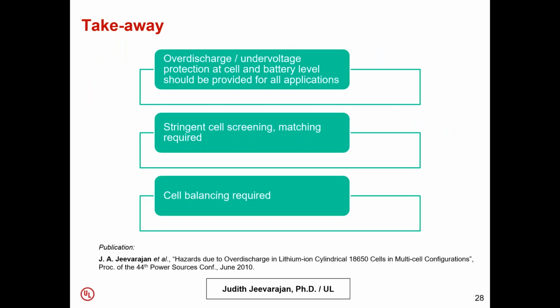So the takeaway from this is that over discharge or under voltage protection is absolutely needed at the cell and battery level for all applications. And if you do stringent cell screening and matching, then you can avoid the deviations in voltage between the cells, and thus prevent any one cell from going into lower voltage than the other cells or going into an overdischarge condition. And cell balancing also helps with this to keep the cells balanced within a small delta voltage value.